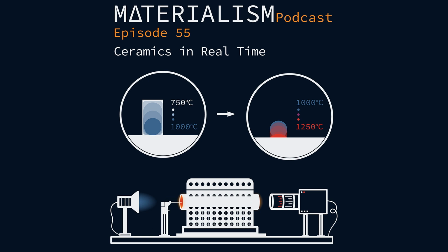But if you put a fired material with the glaze layer upon it, very similar to a finished product, if you take a tile out of the furnace, cut it, and put it on the instrument, you discover really interesting things. For example, you can discover the tension state between the glaze and the body. You have an indirect measurement, of course. There is no way to see the tension state of a material, as we all know. But you have a method to discover it: you heat it up again, and by heating it, it will deform up or down because of the different thermal expansion of the two layers.